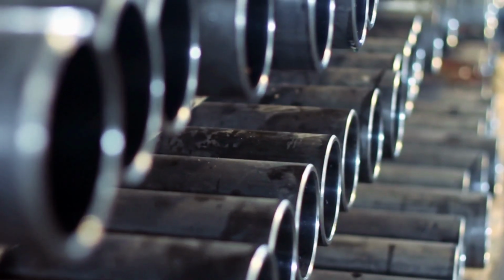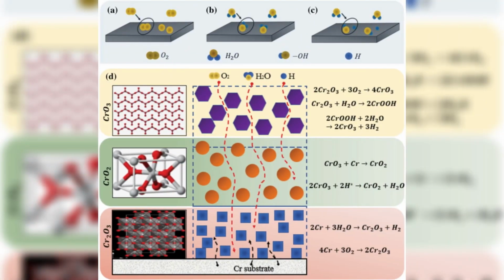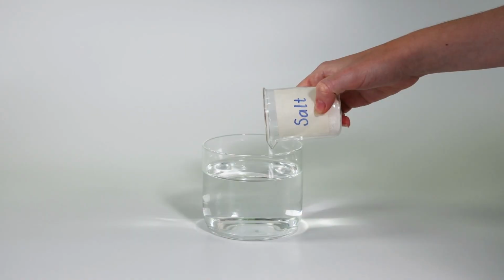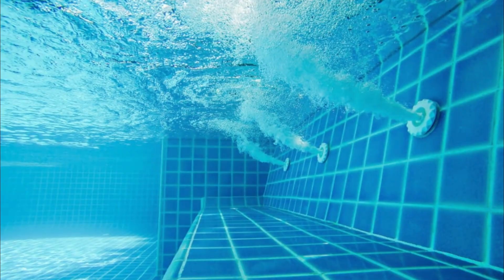So, if chromium oxide is this effective, why does stainless steel eventually stain or corrode in certain conditions? The answer, as is often the case in history, comes down to what the passive layer is and is not resistant to. Chromium oxide provides robust protection against oxidation from air and water. It is significantly less resistant to chloride ions, which disrupt the electrical structure of the oxide layer and can create localized sites where iron beneath is exposed. Salt water, chlorinated swimming pool water, and prolonged contact with salt residue on a surface can all compromise the passive layer faster than it can reform.